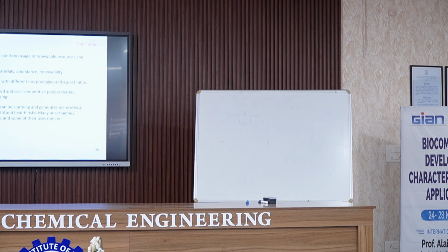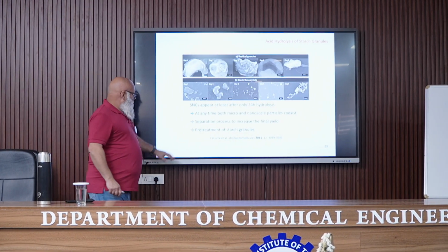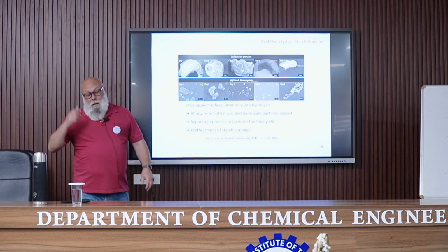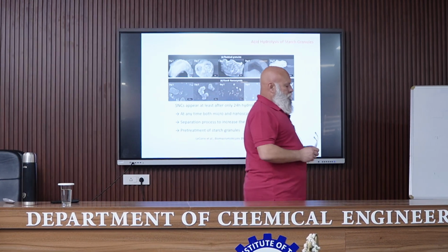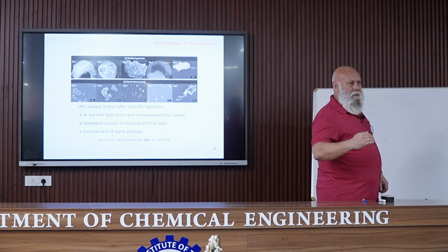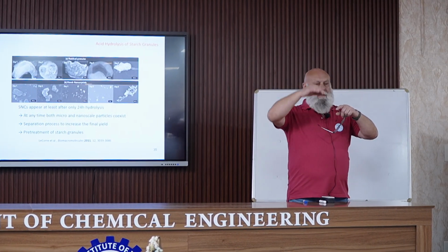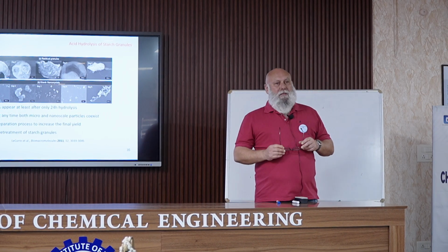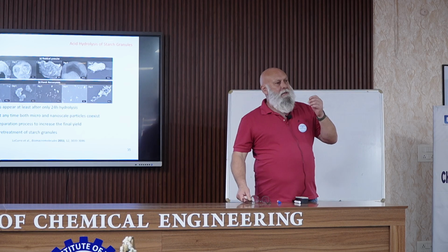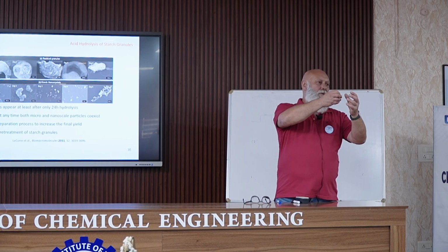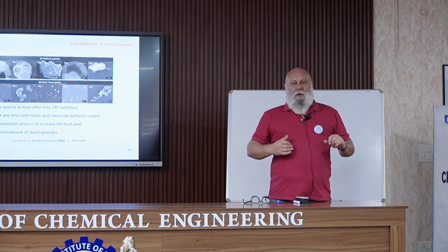Now regarding the strategies that have been proposed, it's not described here. I have to remember. We tried selective permeation of the nanocrystals, so they can only pass if they are at a given particle size, but it was very difficult because the starch nanocrystals that form usually aggregate on the granules, and so they are very difficult to separate.